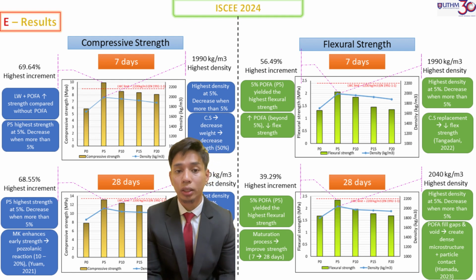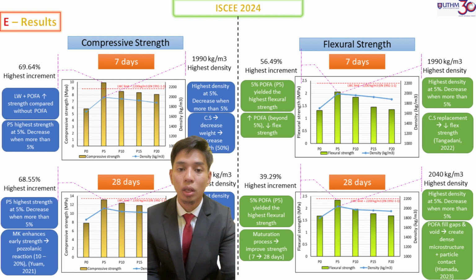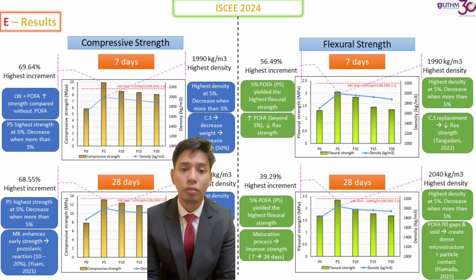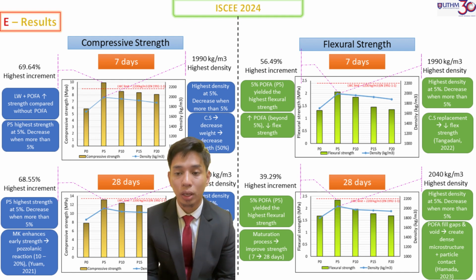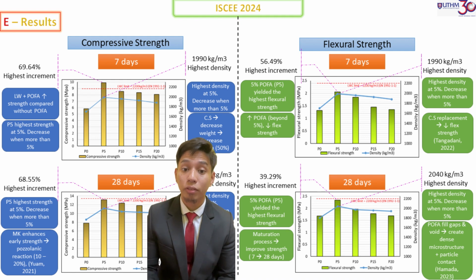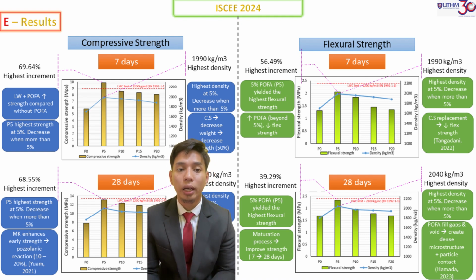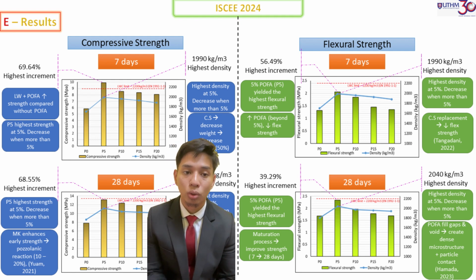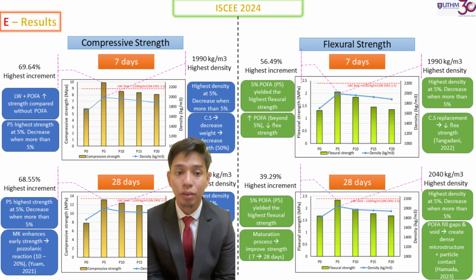The same pattern is shown at 28 days, where the highest flexural strength is recorded at P5 with a 39.29% increment from the P0. So this is for the 5% of POFA yielding the highest flexural strength. The strength increase occurs because of the maturation process, which improves the strength from 7 days to 28 days. And the highest density is also recorded at P5 with 2,040 kg per meter cube. So POFA will fill the gaps and voids, creating dense microstructure particle contact.